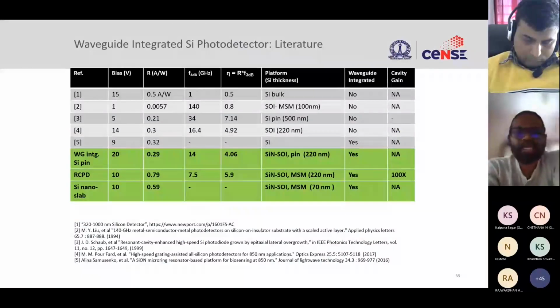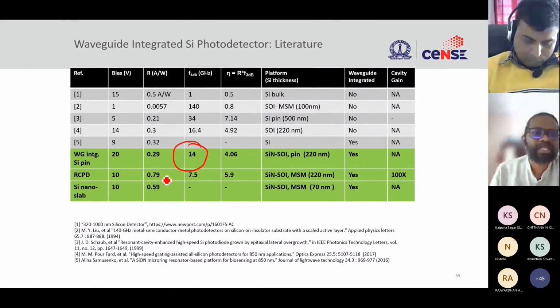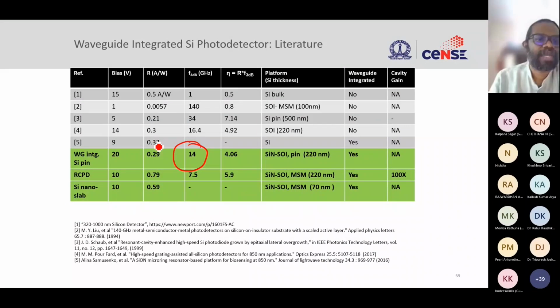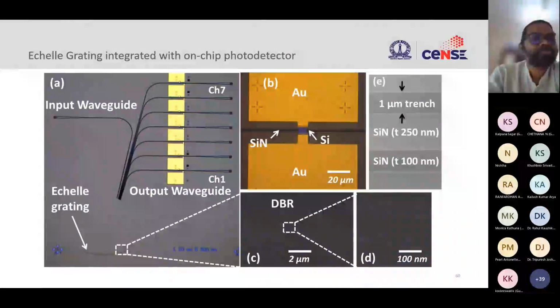But the bottom line here is what we have demonstrated in terms of speed and responsivity. This is really beyond any earlier demonstrations. You're talking about 0.8, 0.6 amp per watt, which is better than the best that was earlier. So these are all state-of-the-art detectors that you can do.